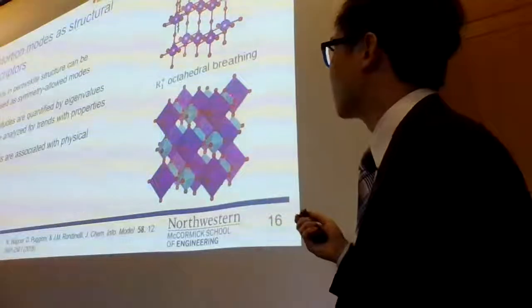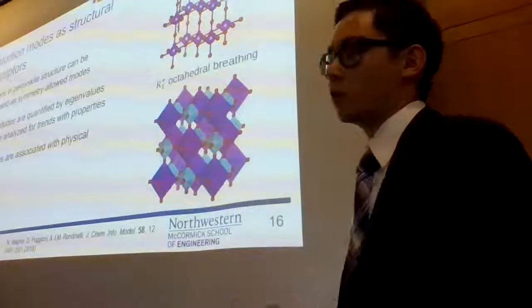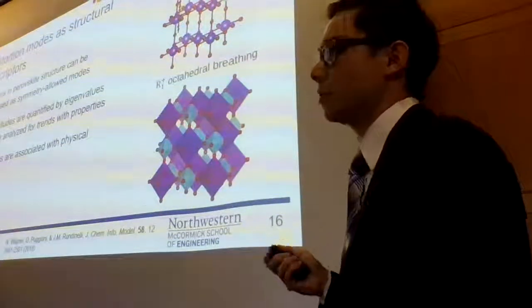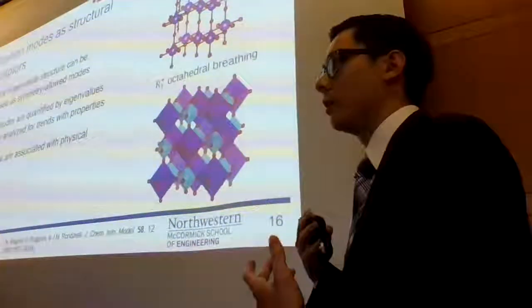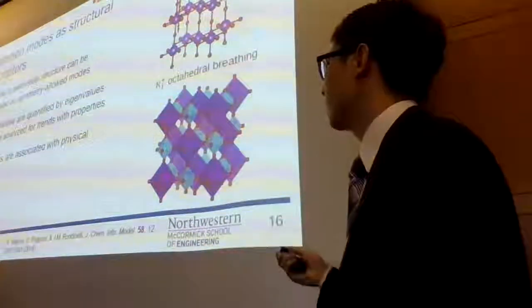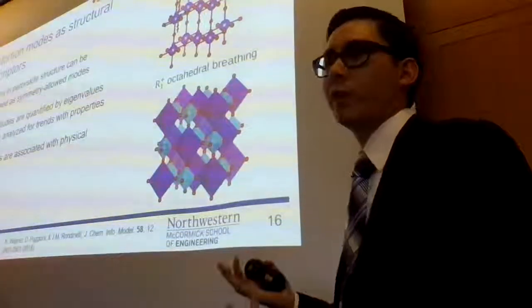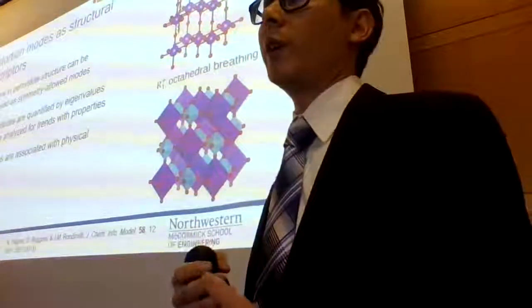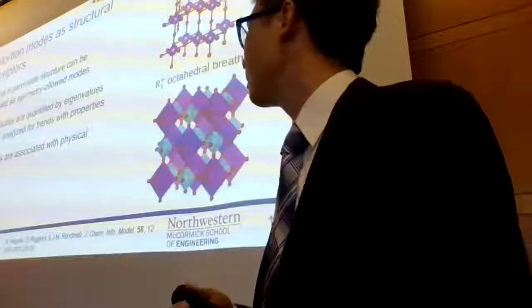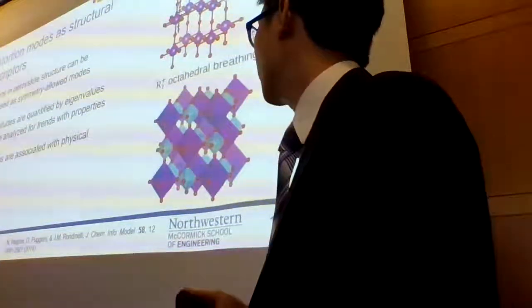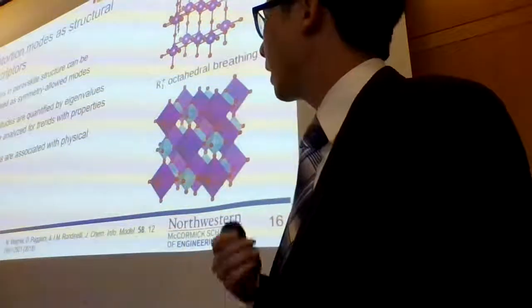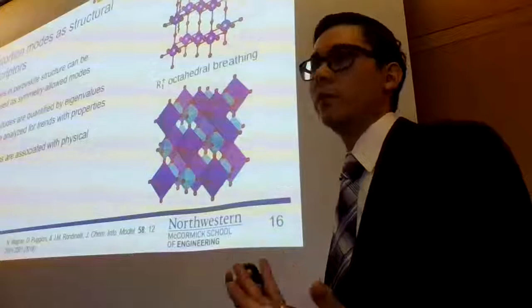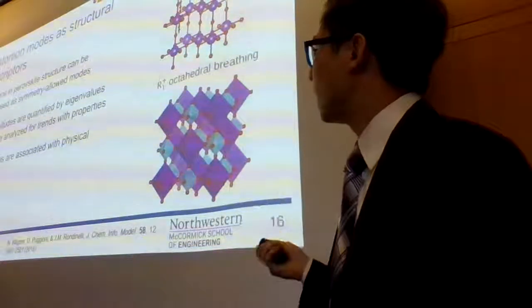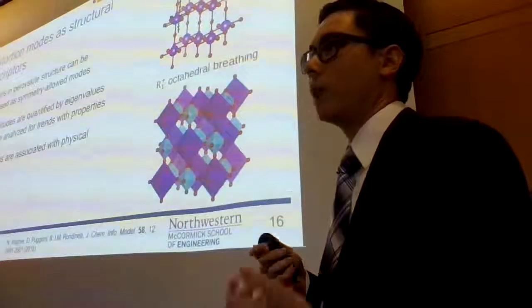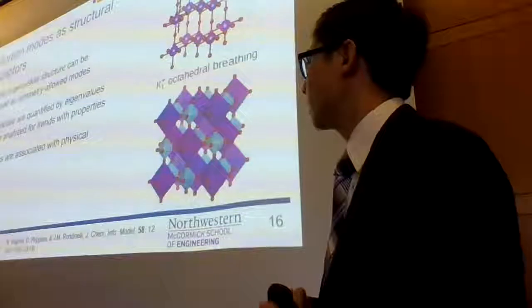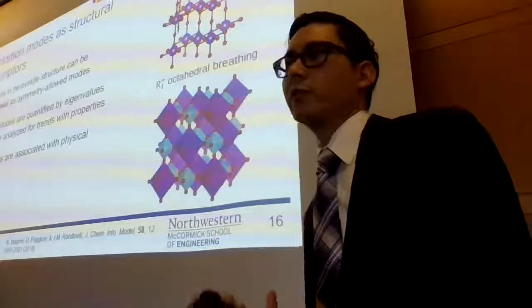Another mechanism that is potentially occurring is this octahedral breathing, which is related to charge ordering. The smaller octahedra, this is exaggerated by the way, would be nickel sites where you have a higher oxidation state than on the purple site. So on average you might have nickel d7, but one site might order into d6 and another site might order into d8. That could also lead to a sudden inability to conduct electrons due to the charge ordering. Different people have proposed different experimental confirmation of one theory or the other. I was interested in whether the magnitudes of these distortions from the mode decompositions could give you some insight into which physical mechanism is occurring.